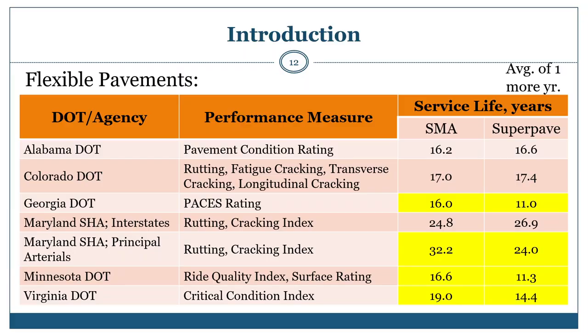In fact, for those agencies that have reported longer service life for the Superpave mixes, the average is slightly less than 1 more year of added service life. Conversely, the average added service life for the other agencies that have reported higher service lives for SMA mixes is almost an average of 6 additional years of service life for SMA mixtures compared to the Superpave mixes.